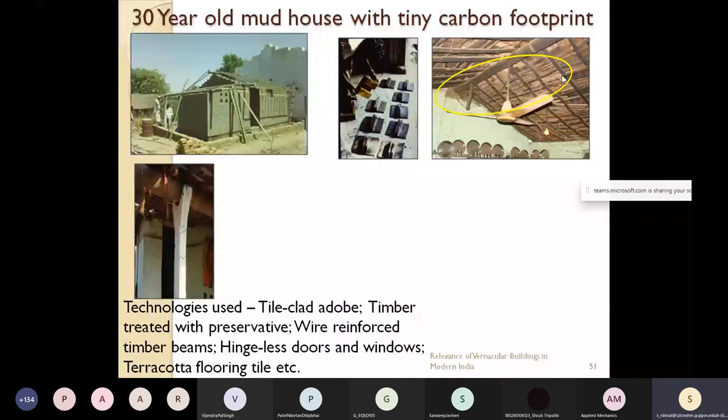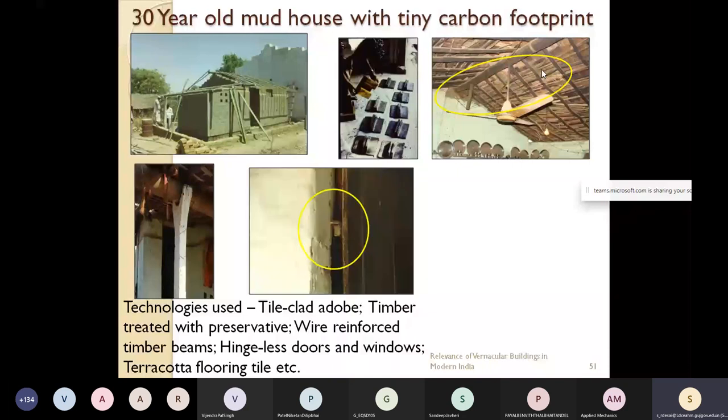Here was the precast column we had made, because this is something that goes in the ground and it rots very fast. One more thing I want to mention here that we are very proud of. The timber you see in the roof is all treated timber, basically eucalyptus. Imagine, in 1990 we built the house and still it survives. All that timber, which typically would have deteriorated completely in 5 years, has still survived because we carried out a hot and cold treatment on site. All right. So today, timber should be used and can be used, but with preservation. And this is the most versatile material and it should be promoted.